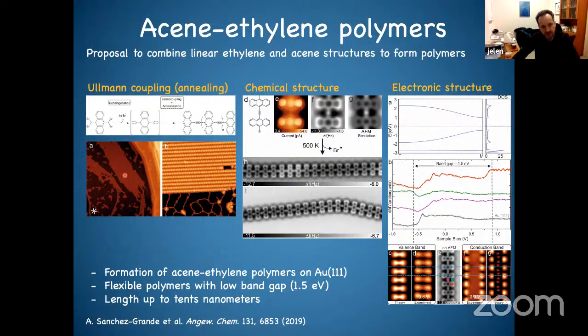So you put this in UHV, we anneal it on the gold, and then you start to see very nicely ordered chains growing, which are tens of nanometers long. And then we use high resolution imaging, which you see here. So this is the AFM, the chemical resolution of this polymer on the surface. And we can also use scanning tunneling microscopy to reveal the conduction and valence band.